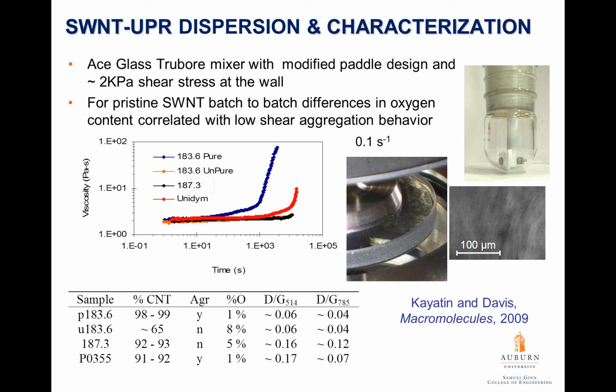Going back to the nanotube UPR work that I mentioned earlier, we were able to look at several batches of supposedly the same material, single wall carbon nanotubes made by a similar process, and we looked at viscosity, or the resistance to flow, versus time. What we found was that for some of these batches, the viscosity would jump up after a long time, and that corresponded to the formation of aggregates that we could actually see with our eyes. Obviously, this is not going to make a cohesive structure, whereas other batches didn't show this behavior, and that gave us a very uniform structure and a much better final resin.